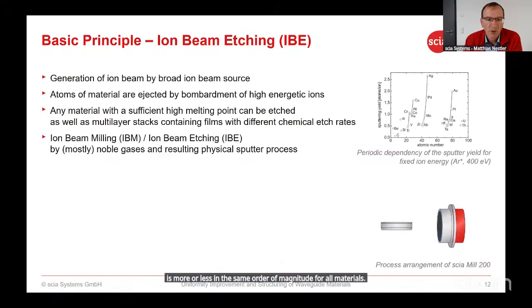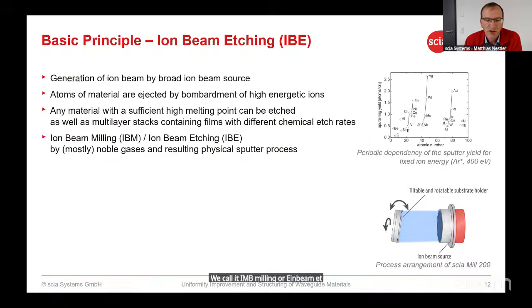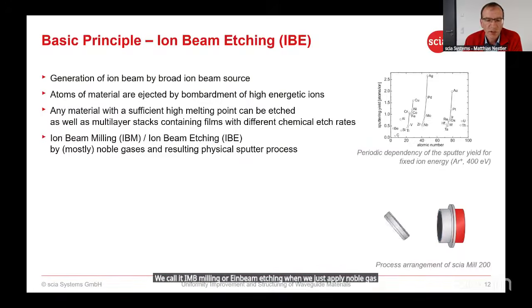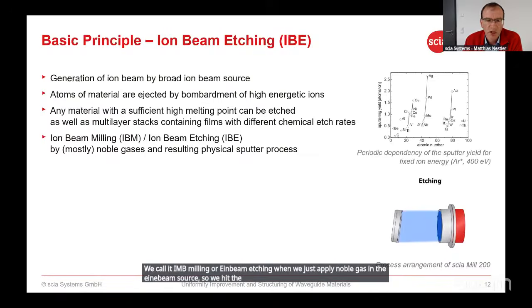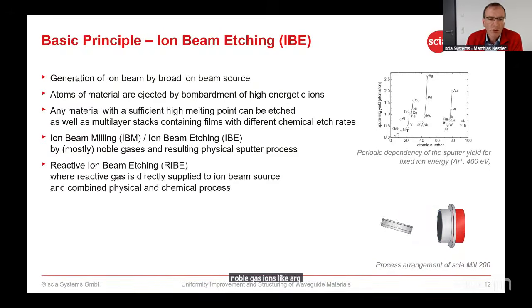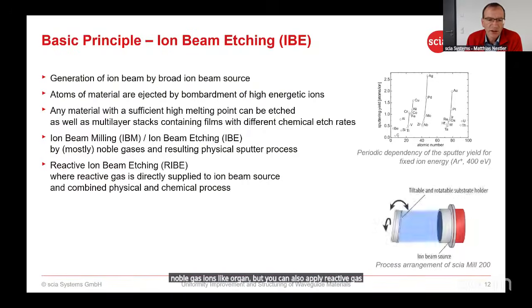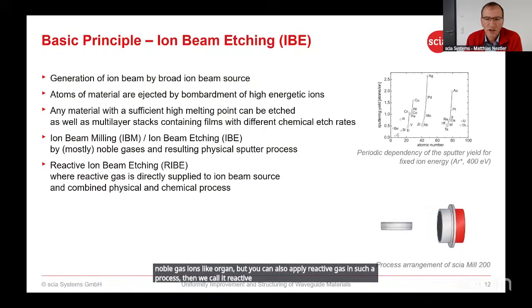We call it ion beam milling or ion beam etching when we just apply noble gas in the ion beam source. So we hit the surface with noble gas ions like argon. But we can also apply reactive gas in such a process. Then we call it reactive ion beam etching. So we increase the etch rate and some selectivity.